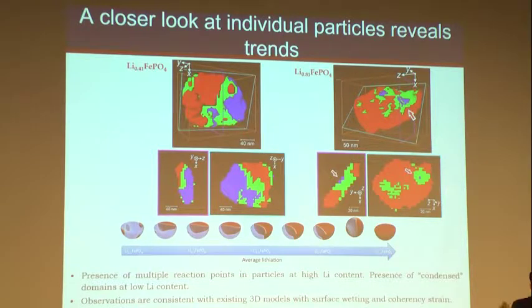These at first seem to be just an observation and nothing else. Around the same time that we did these measurements, there was a paper coming out of Argonne where they modeled this system in 3 dimensions, using considerations of phase diagram, thermodynamics, coherency strain, and surface wetting. This is the result taken from this paper. What we found intriguing is that in their case, they were seeing similar effects: at low levels of delithiation or lithiation, there would be spots in the particle that were active, and in the intermediate states, you would see more condensed domains.